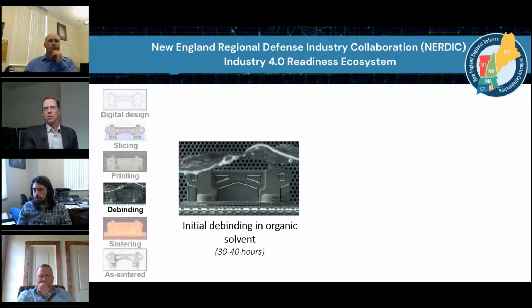There are maximum thicknesses that we can run the walls. But the debinding time just depends upon how thick those walls are, and you can batch these jobs together. So you typically print 3, 4, 5 parts, and then you take them, put them in the debinder, run them as a batch for 30 to 40 hours, and then they're ready for the sintering process.